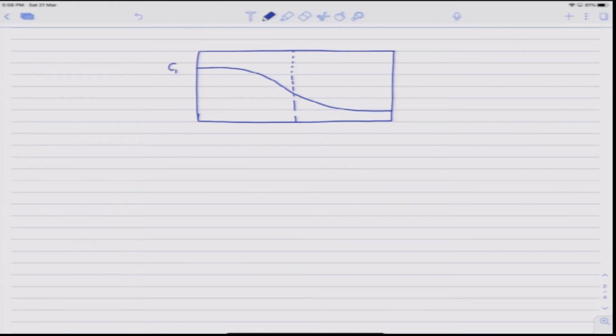The left terminal alloy concentration is C1 minus, the right terminal alloy concentration is C1 plus, and suppose we placed some inert markers at the initial interface before the diffusion started, and after the diffusion annealing for time t, let us say the markers have shifted to position xk. This is the Matano plane position x naught here, which is the initial contact plane.